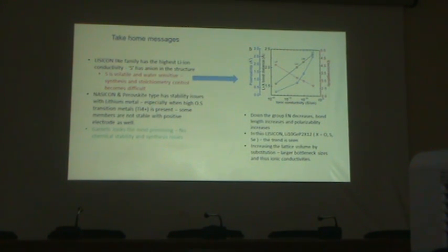Bottlenecks in solid state diffusion basically mean all the drag and electrostatic attraction an ion can feel when it is moving. Structurally also, in the earlier talk we discussed lithium iron phosphate having one-dimensional diffusion and spinel having three-dimensional lithium diffusion. Normally in a battery we would like three-dimensional diffusion, which would be perfect. But in lithium iron phosphate you don't get that. Because of the way lithium is distributed in the layers, you get movement along one particular direction.